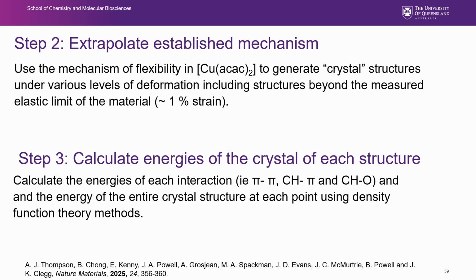The next thing we needed to do was create a lot more data. We only had about 20 data points from our mapping experiments, right? So not quite enough to model these things. So we need to do some extrapolation. But because we know the mechanism, we can use some linear algebra and some matrix calculations to do that. And so we generated about 200 different crystal structures, hypothetically, under various levels of deformation. So ranging from 0 to where we know the elastic limit of about 1% strain and even beyond. And then we calculated the energies of every single position of those. And we started to look then at what they meant.